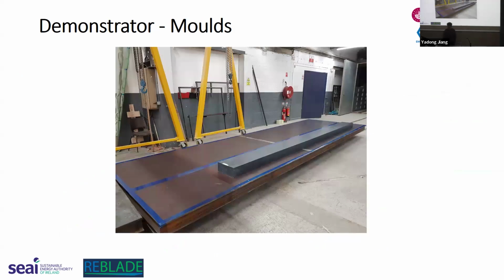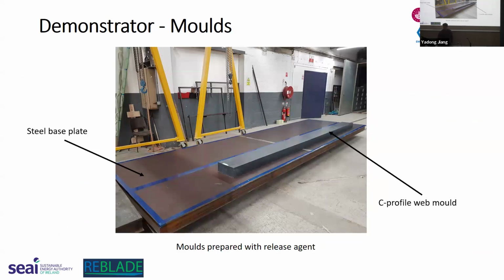Demonstrator molds then, this is simply how we manufactured the surfaces that we use to manufacture the components. So we have a flat steel plate, and then we have a C-profile web mold to make the web components. The molds are prepared with release agents so that when we infuse them, they don't stick to the base plate or the web mold.